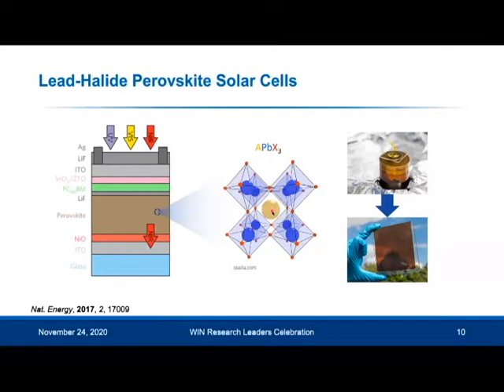And what's rather unusual about the perovskites is that they can be made at low temperature using solution processing methods. So you spin coat these films, you anneal at just 100 degrees Celsius, and you can make solar cells that are almost as efficient as the best single crystalline silicon solar cells. Now, if you contrast that to silicon, to make the best silicon devices, you have to process at above 1400 degrees Celsius to melt the silicon and draw out single crystalline silicon that you slice up, and then you have to process in a very clean environment. By contrast with the perovskites, you can process them inside a normal lab-based glove box or inside a normal dry lab, and just anneal at 100 degrees Celsius to get these high efficiencies. So the CO2 footprint of manufacturing perovskites is also a lot lower than that for making crystalline silicon devices.